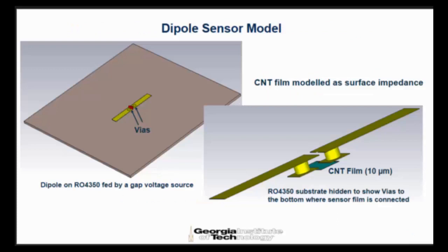So first, we did some simulations. This is an example of the dipole. There are two vias going to the other side. There is no ground plane on this. It's a simple dipole. And I put a film in the gap on the other side, 10 micrometers thick single wall nanotube film, with nanotubes very specific to ammonia. And we did this on a Rogers substrate.